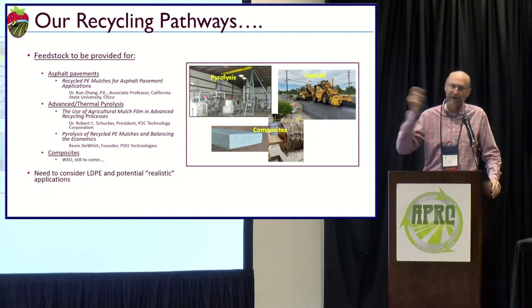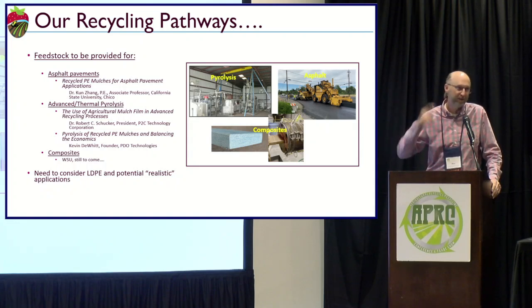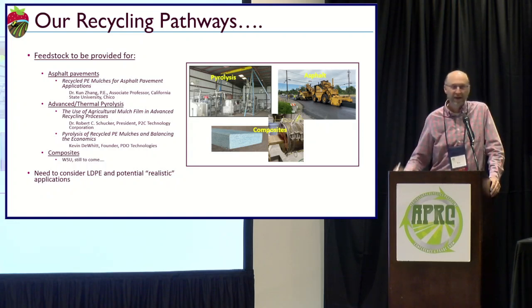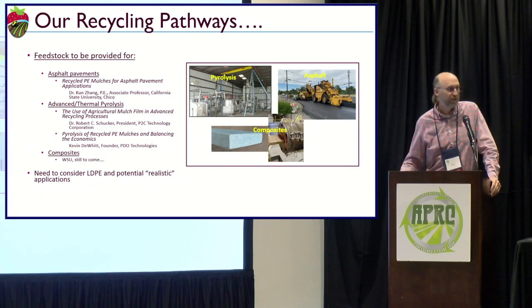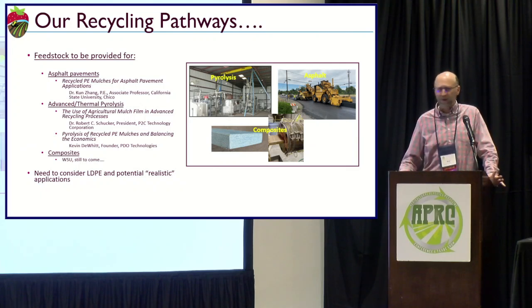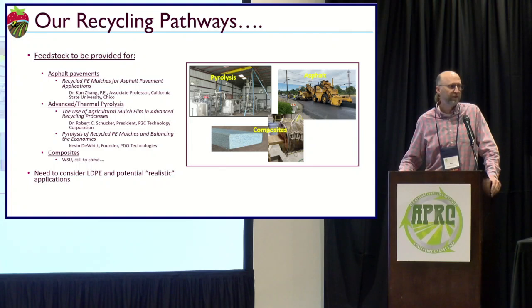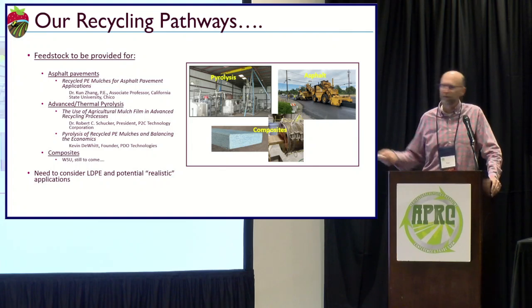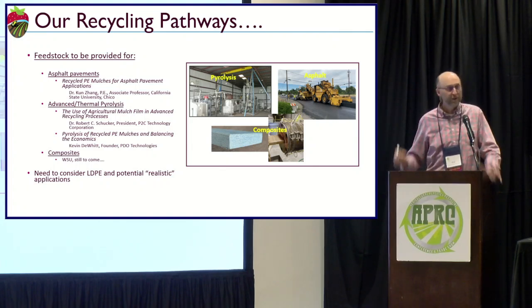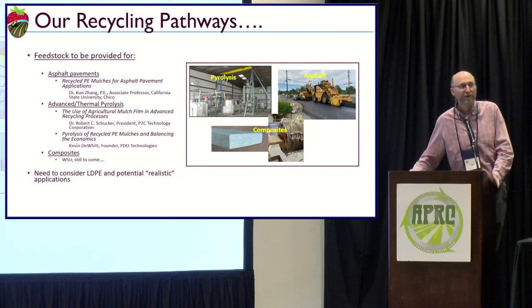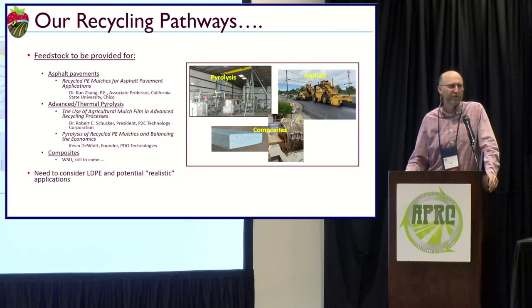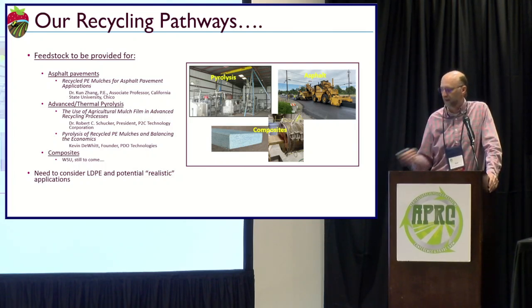When you start adding all these contaminants and you put all this different material in there in the recycled material, you might get some gel from the crosslink with the UV. All that's going to affect your blow capacity and how this material is turned into films. And so finding other applications besides it going back into a film, it doesn't mean you can't put it back into a film, but not putting it back into a film is probably the best way to do it if you want to make it economically viable.